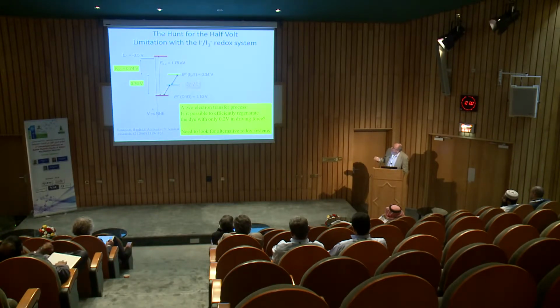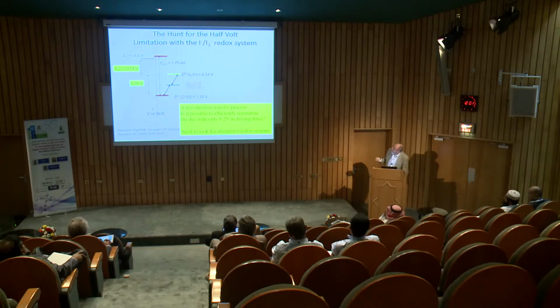And if you do that and keeping this level constant, you would redshift the dye and you hope for a higher current, let's say. But the potential is given by the Fermi level of the TiO2 and the redox potential of the electrolyte. So by moving the dye state up here, you hope for a constant voltage but higher current. Now it turns out that with the iodide system it's not so easy to reduce this potential drop so much. You will lose in regeneration kinetics.